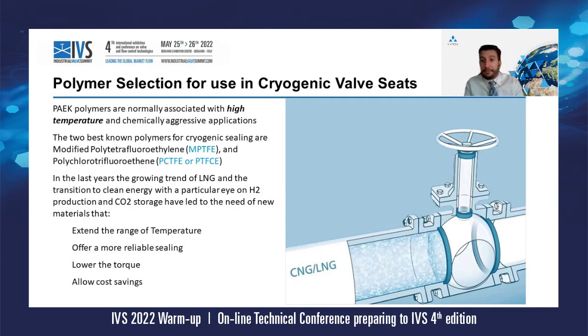The problem is that today, PCTFE is no longer capable of covering the increasing range of temperature that cryogenic valves are seeing. It's become quite common that the end user asks for cryogenic valves which work from -196 to even +200. And consider that 400 degrees is a huge, very wide range of temperature to be covered consistently. So PCTFE is surely a material that doesn't help reduce the torque. It's not cheap and it has certain limitations.